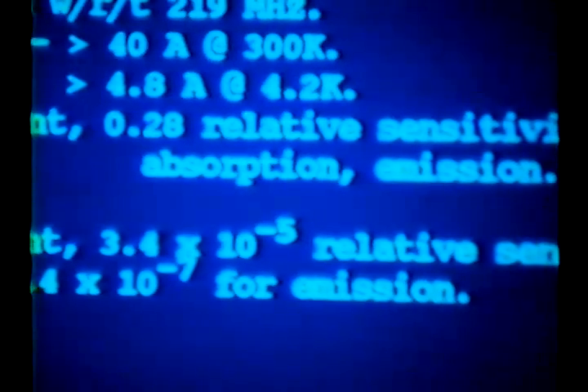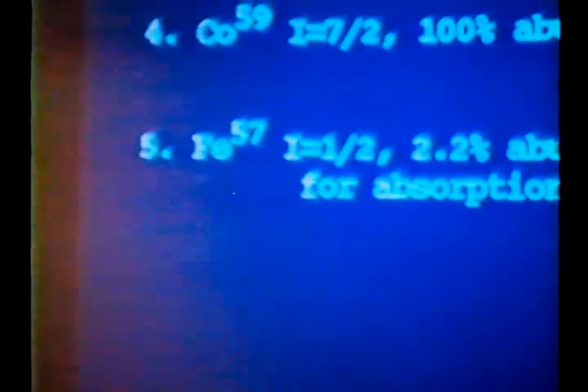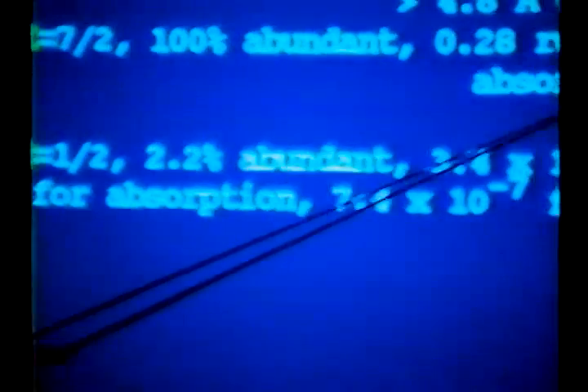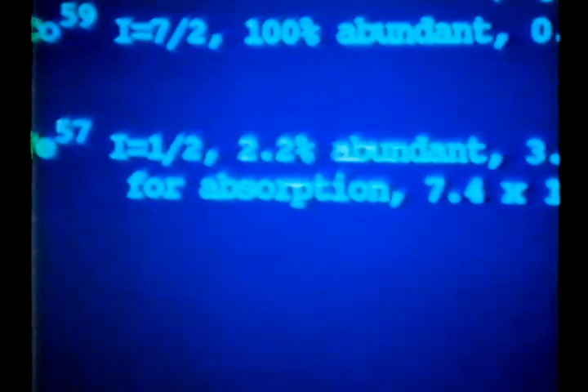Why cobalt? Well, cobalt has a 100% abundant spin of 7/2. That's the reason. That's the good news. Iron 57 is only about 2.2% abundant. That's the bad news. It's tough to do this experiment on iron unless you label the material. Cobalt also has pretty high relative sensitivity and absorption, while iron 57's sensitivity is also quite low. So it's easiest to do this experiment on cobalt.